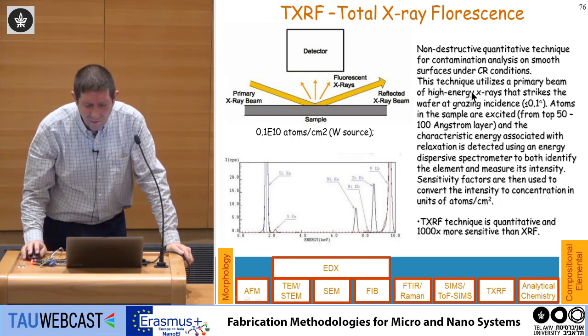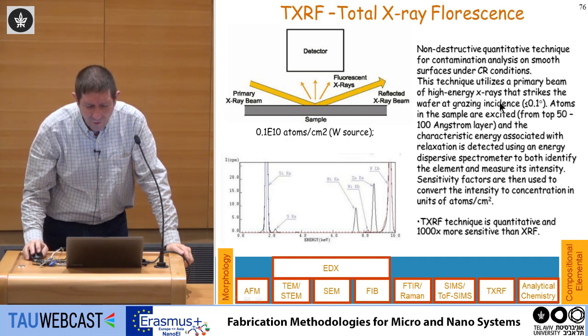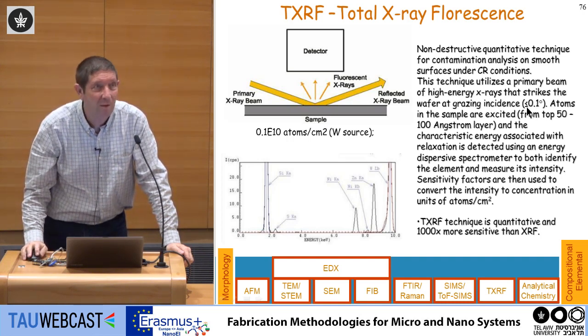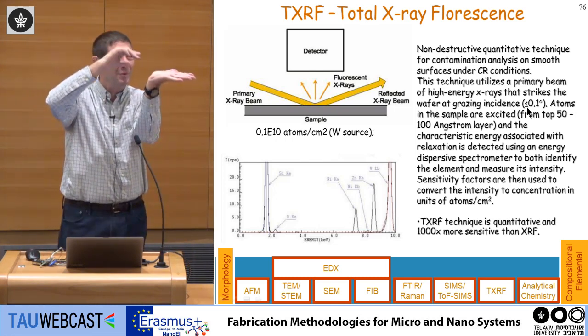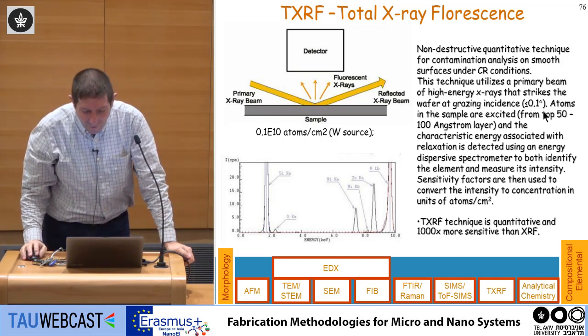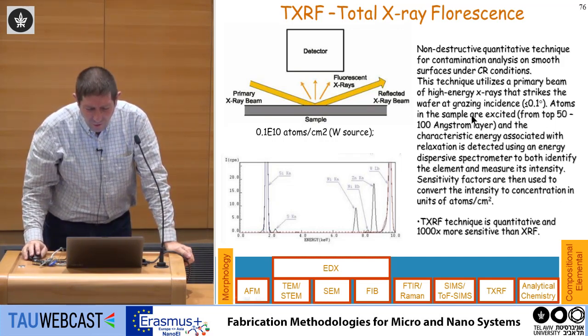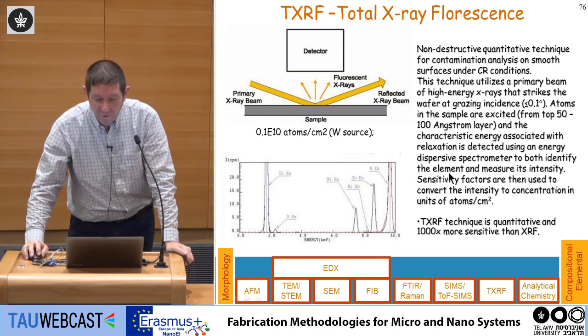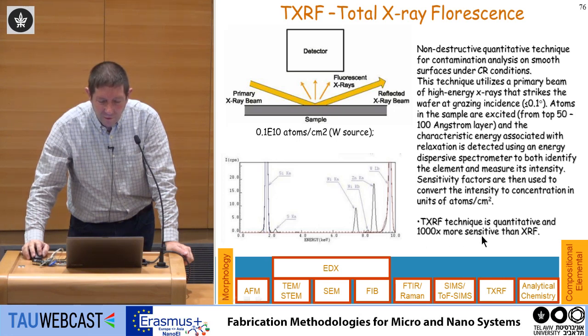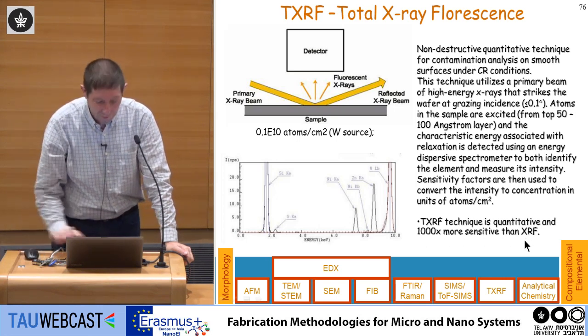This technique utilizes a primary beam of high energy that strikes the wafer at a grazing incident angle of less than 0.1 degrees. So you have to really align the surface and the beam; it has to be very precise. The atoms in the sample are excited from the top 50 to 100 angstrom level, and the characteristic energy associated with relaxation is detected using an energy dispersive spectrometer to both identify the element and measure its intensity. Sensitivity factors are then used to convert the intensity to concentration units. As I put here, it is about 1,000 times more sensitive than regular X-ray fluorescence.